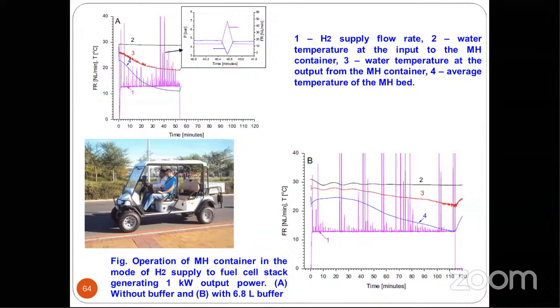Next, we added some buffer cylinder. Then we supplied the hydrogen from both. So you are taking less hydrogen from the metal hydride cylinder compared to the previous case. Obviously, the heat requirement will be less, and whatever heat you are supplying with water will be more than enough to keep the temperature constant. Here you can see the temperature decreases, but not much compared to the previous case, because we are taking hydrogen from both the buffer cylinder as well as the metal hydride container. This operation continued almost 2 hours without any problem.